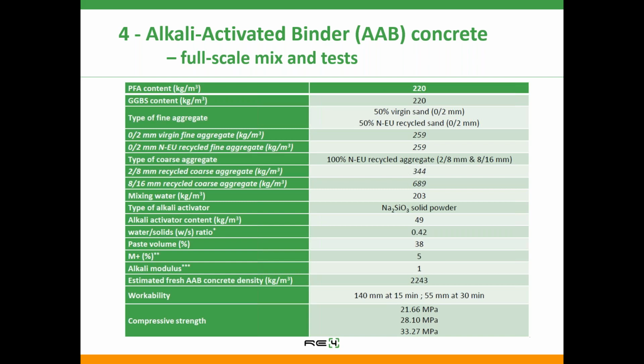The alkali activated binders, we've got the full-scale mix and tests. This is without using cement, so instead fly ash and GGBS was used. So total binder content was 440. Again, I repeat, there was no cement, it was just fly ash and ground granulated blast furnace slag. We used 50% newly quarried sand and 50% recycled sand. The coarse aggregate was all recycled aggregate. Activator was sodium silicate, and the strengths obtained were from 20 to 33 megapascals.